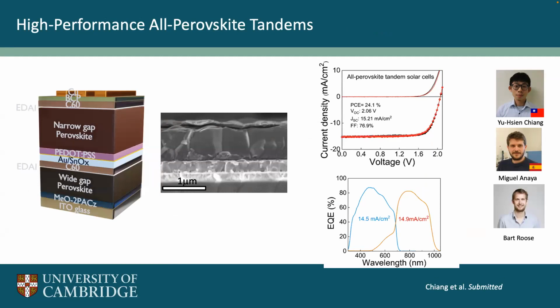And then this is our recent work on the tandems, the perovskite tandem solar cells. This is looking at, remember where we have the wider gap cell and then the lower gap cell, and this is a cross section here, and we've got some really nice results now. This is a 24% tandem, which is one of the best in the world, in fact, for these all perovskite tandem solar cells. And again, this efficiency is ramping up very quickly as well. Remember, we can practically get to something like 35%. There is still a nice window to go up even higher.